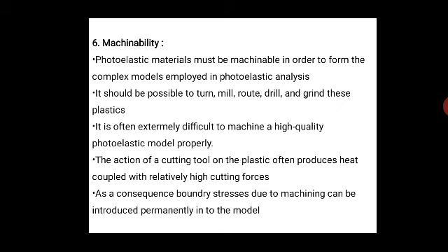The important thing is that the photoelastic model is mounted to a metal template which describes the exact shape. The template is guided by the oversized diameter pin of the file, and the rate of feed along the boundary of the model is carefully controlled by moving the model along the pin by hand.